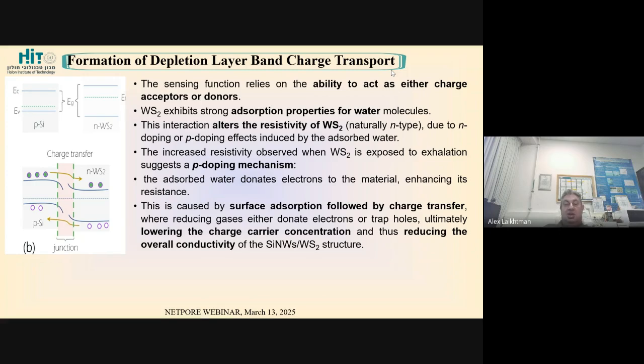And water absorption is quite strong on the nanotubes. Sometimes we don't want this, but for breath testing, it proves to be beneficial. So there is interaction. This interaction changes the resistivity of WS2, which is naturally N-type, due to either N-doping or P-doping, and then the absorbed water donates electrons to the material, enhancing its resistance.